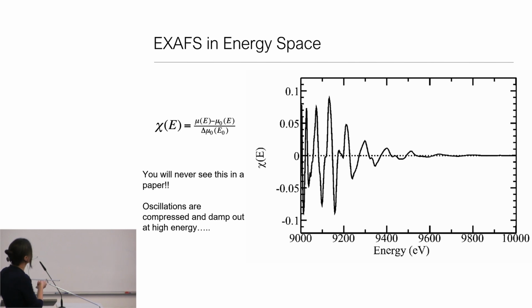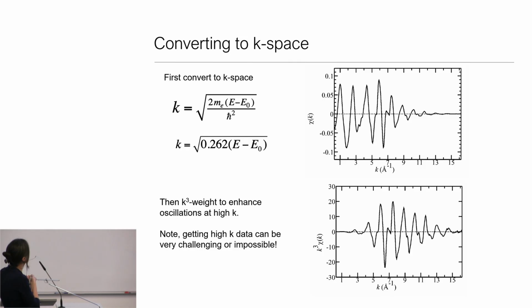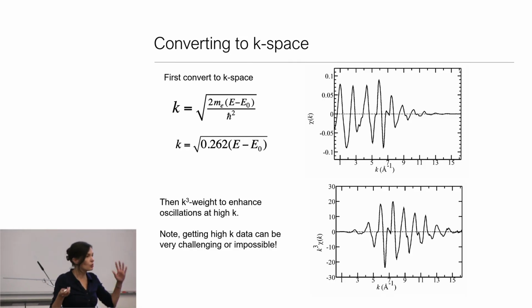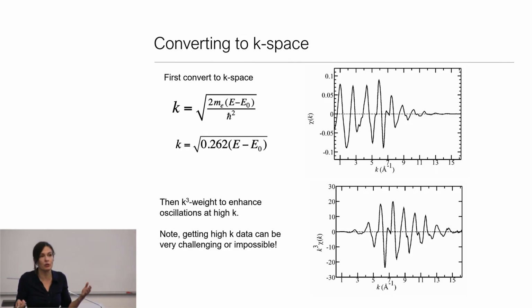So first we do that subtraction, and then we have basically something that starts to look like EXAFS, but it's all compressed because this is EXAFS that I've kept still in energy space. And then in the next step, I convert energy space to K space. So here's the equation for that. You can see I have to define E0, and this is a problem because I don't actually know where E0 is, right? It's somewhere around the edge-ish, but to say exactly when something's been excited to the continuum, I can't a priori know.